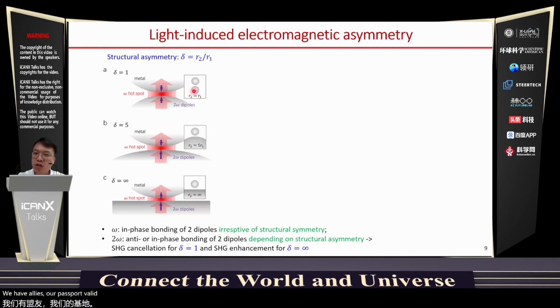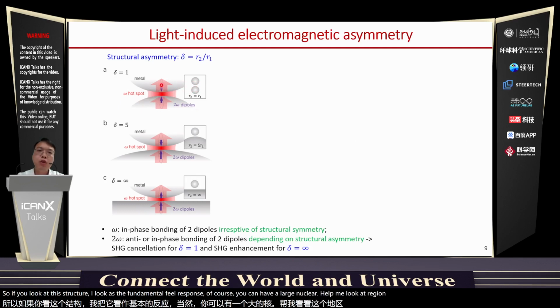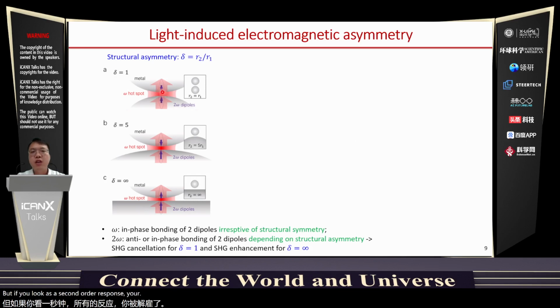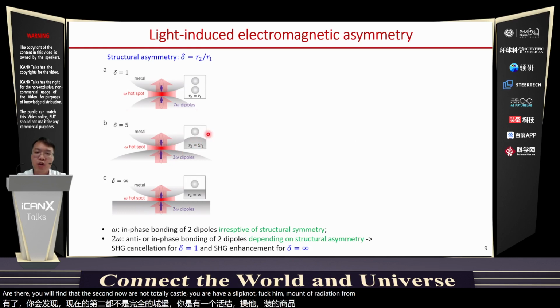The first structure is a symmetrical nanoparticle dimer. If you look at this structure and the fundamental field response, of course, you can have very large near field enhancement in the gap region. But if you look at the second order response, you will find that the second harmonic dipoles in this structure are anti-parallel to each other. So they will cancel out in the near field regime and give you very weak second harmonic generation. But the good thing we found here is that if you increase the dimension of the second nanosphere, for example the bottom one, then you will find that the second harmonic dipoles are not totally canceled. You will have a certain amount of second harmonic radiation from this structure due to the symmetry breaking.